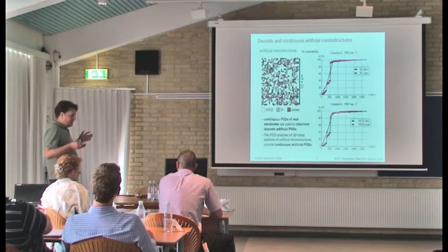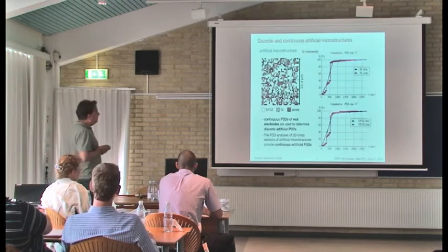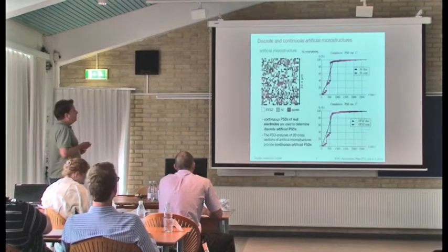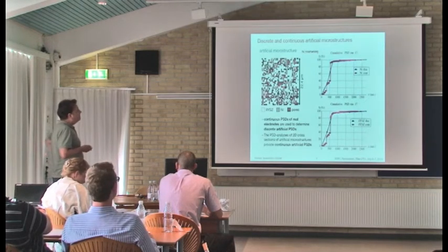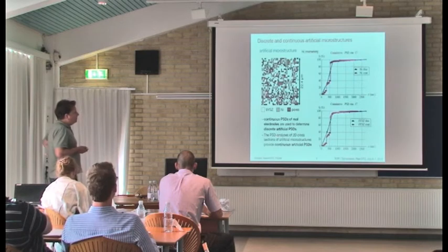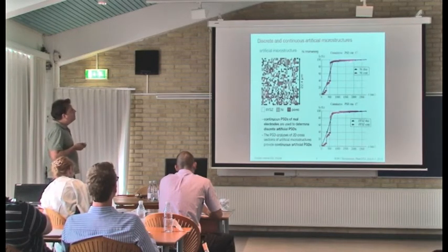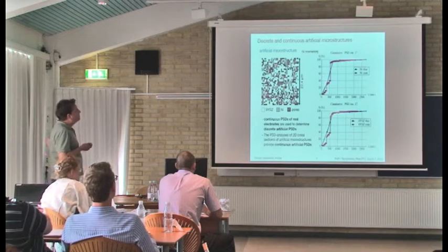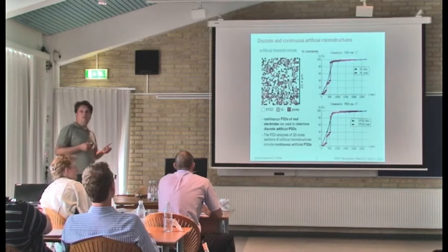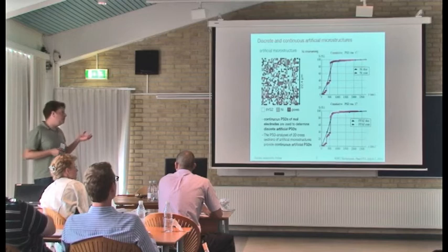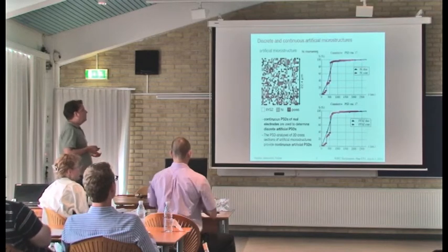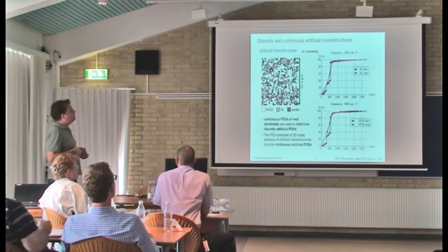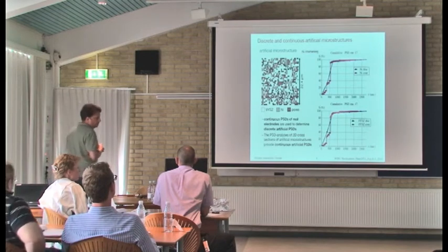Now I simulate my sintering process. I put them together to get my microstructure. Then I send these images back to Lorentz, and he analyzes them again with the same algorithm. What he gets is this red curve here. So you see, it's not a perfect agreement, also due to the fact that I'm rather coarse here in my particle size distribution, but for now it's close enough.